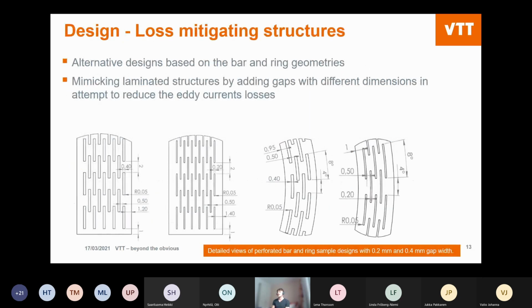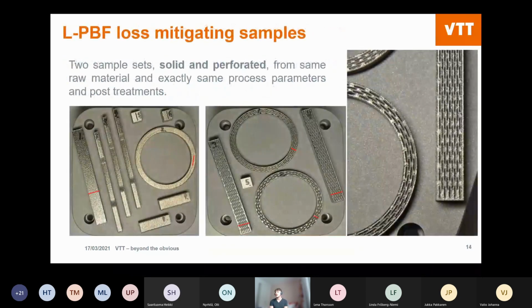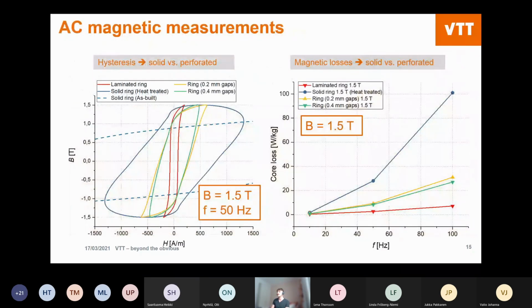Some of the first things we tried, as was also shown in the approach by other research groups, was to use the geometry of the component, so a clever design, to introduce gaps into the material to prevent the progress of the eddy currents. Here you can see the printed samples. We made these bar and ring samples using laser powder bed fusion, and we made the same things as a bulky solid, and then with holes in the material to prevent the progression of the eddy currents. And here you can see the results for the losses.